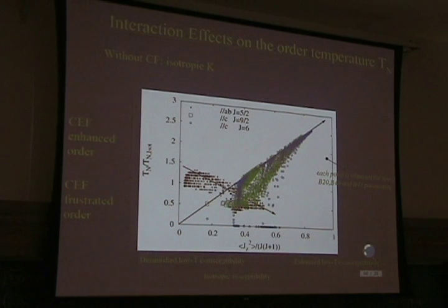And we can do that with many different crystal field parameters. For example, you keep changing the parameters, see if your zero moments are in the plane, and calculate that value. And you're going to plot like this for cerium a suppression of T_N, and an increase of T_N for terbium and neodymium.